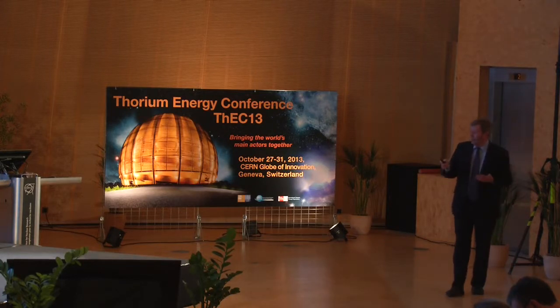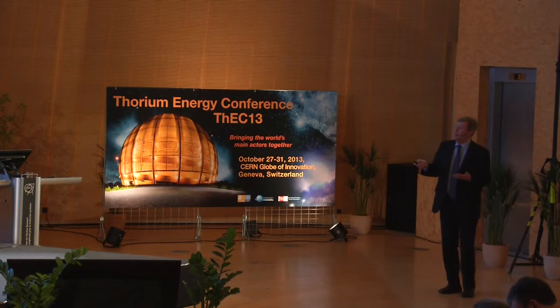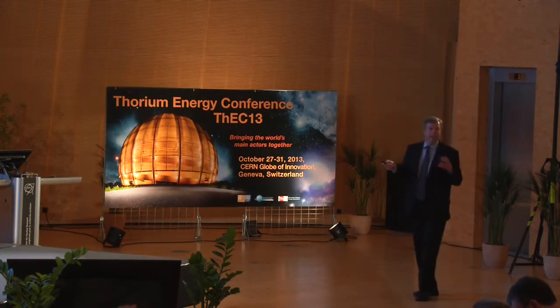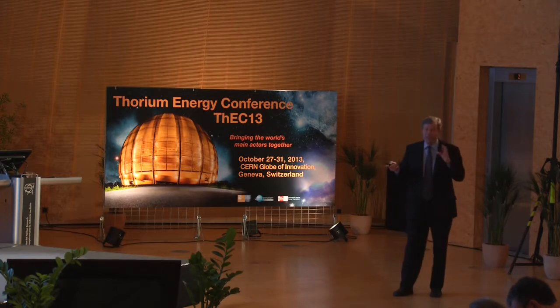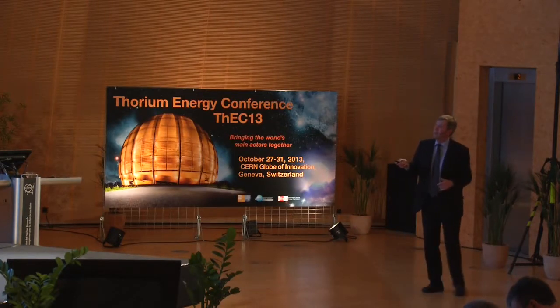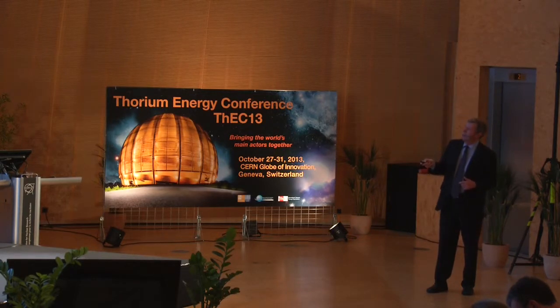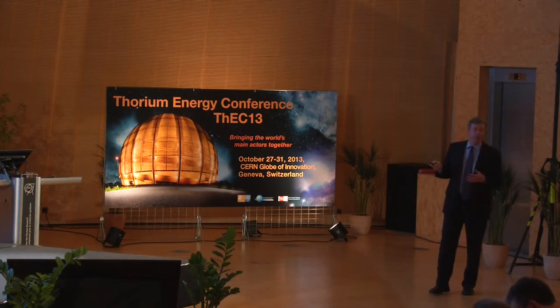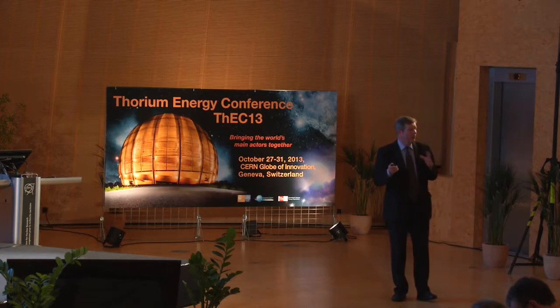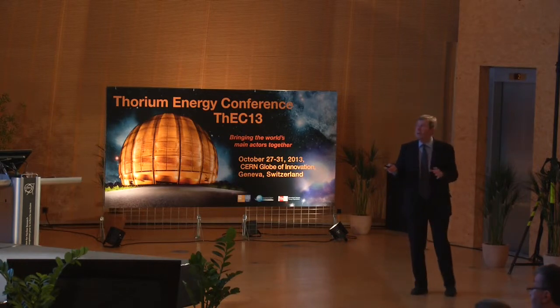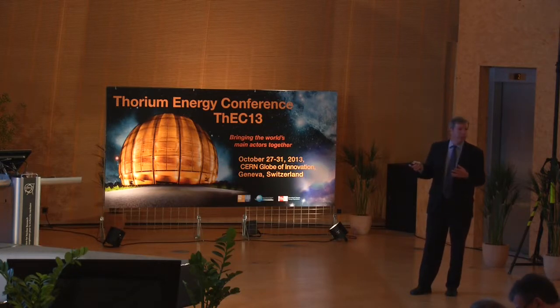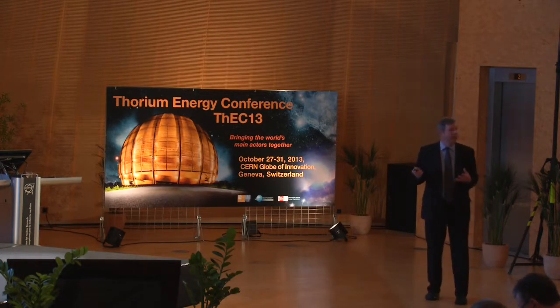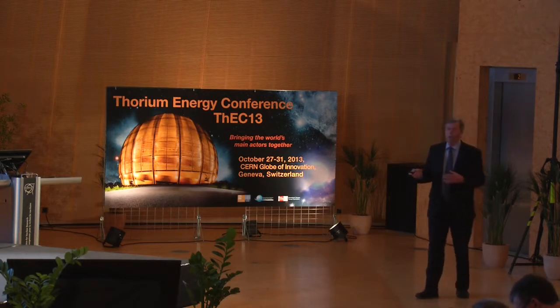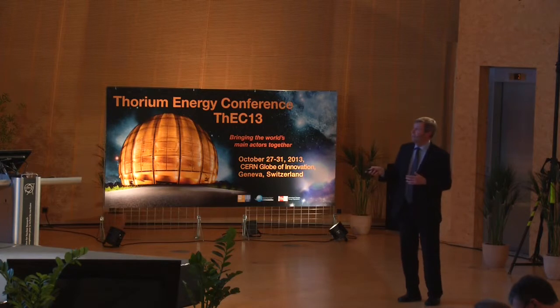So just to illustrate validation, this is quite an old slide, but I've stressed how the structure of the fluid is the key to understanding the influence of the chemical properties on the physical properties. So this is comparing some predictions with these simulation models with experimental data looking at the structure of the melt. So these are X-ray diffraction experiments here. These are neutron diffraction experiments. And this is X-ray absorption fine structure. Each of these experimental probes looks at the local structure in a liquid in a different way, but you can see that this one simulation model is reproducing that data extremely well. So in this case, I can have a great deal of confidence that my simulation model is behaving in the same way as the real material.